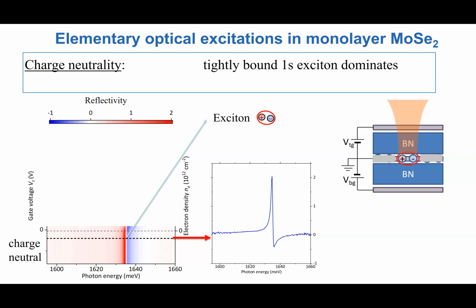There are other 2s, 3s excitons, et cetera, but that's off the scale here. So in the regime that I'm looking at, which is about 60 millielectronvolts, there's only one resonance peak. It's a dispersive line shape, right? Because we haven't really paid attention early on to eliminate the background reflection. The peak reflection is about 2 or so. And then you see that there's this very narrow line. In this case, I think the line width is like 50% larger than the radiative line width.